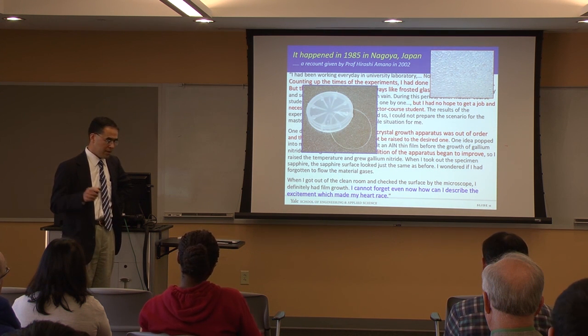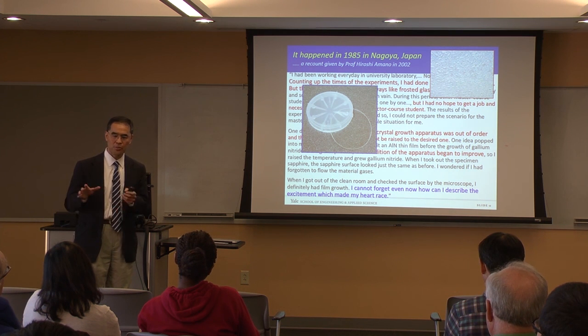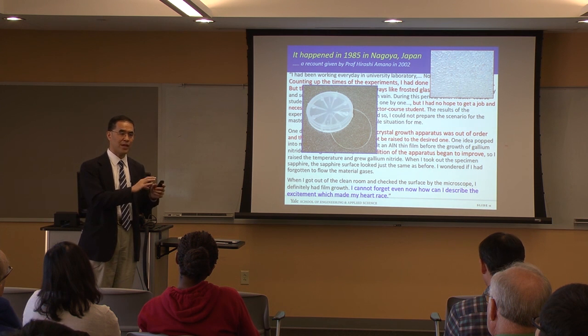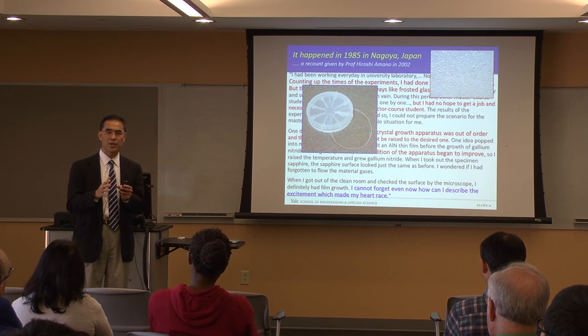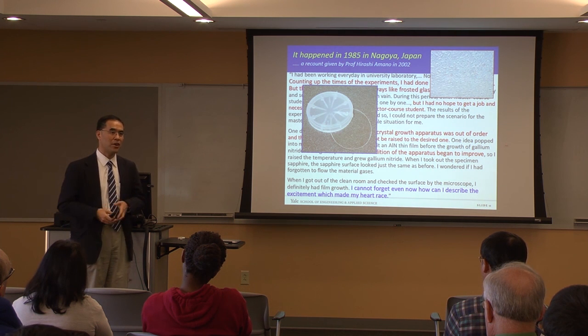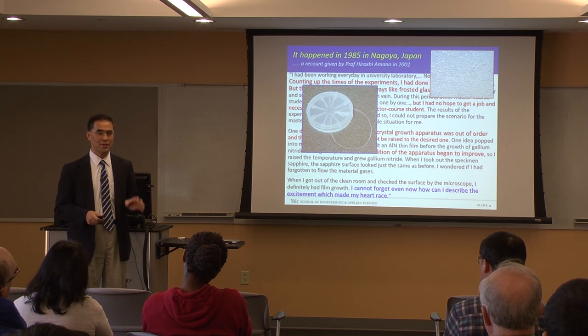So, yes, in fact, I asked Professor Akasaki, his advisor, about this question, and he told me that he feels gallium nitride is a soft material compared to sapphire. Sapphire, in terms of hardness, is ceramic-like, a very hard material. He feels they need a handshaking layer with an intermediate property between a relatively soft gallium nitride and an extremely hard sapphire. In electrical engineering terms, it is an impedance match or transformer sort of concept in material research.